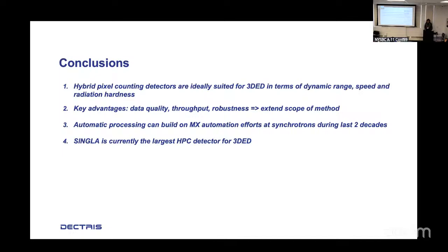So we finish this part. I think that hybrid pixel counting detectors are really very well suited for 3D ED or MicroED because of the dynamic range, the speed, and radiation hardness. They give you very good data quality, a very high throughput, and they are very robust. So even if you're a newcomer, you don't have to be scared. You can put the direct beam on the detector. It will last forever. Unfortunately, as a vendor, we don't like this, but you cannot break it. But it extends the scope of the method because it has this versatility that you don't have to think about the detection.